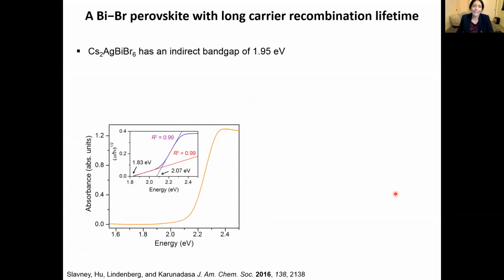And indeed, the band gap is indirect. So that means it absorbs sunlight very weakly, and the band gap is too high for a single junction absorber. There are solar cells which could use this band gap. But the band gap is indirect, meaning that you need a thick layer of this material. So as I mentioned, silicon, which is in the commercial solar cells, does have an indirect band gap. But this is not a problem because you can simply use a thick layer of silicon.